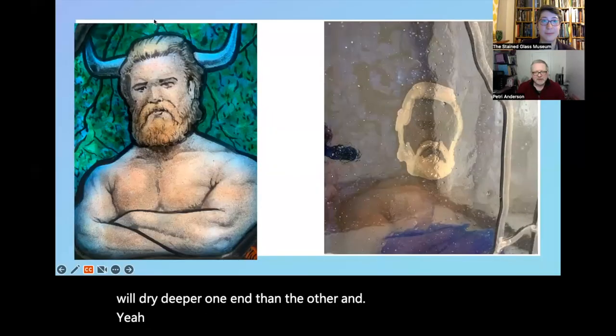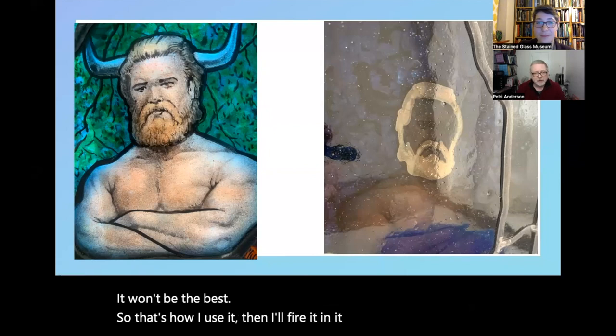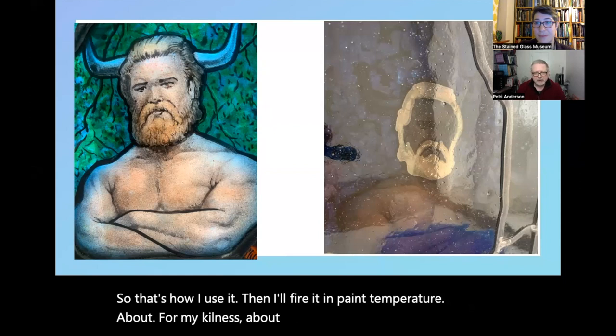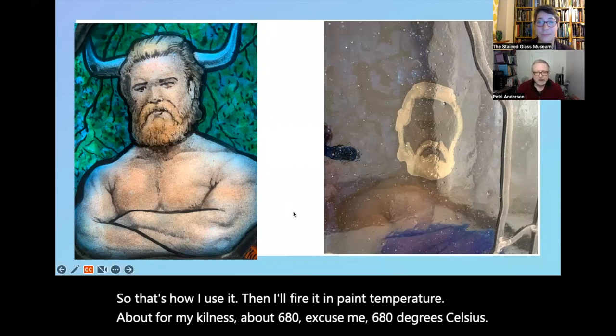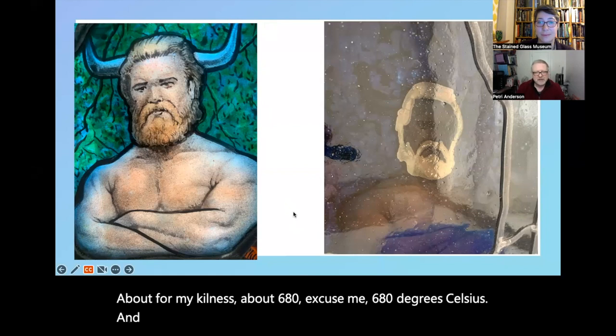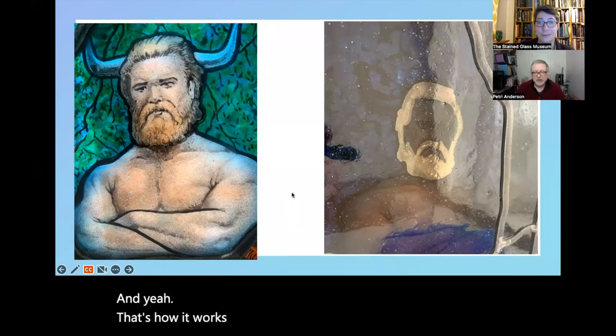And it really works best in small areas. When you try and do a large area with it, then inevitably it will dry deeper one end than the other, and it won't be the best. So that's how I use it. Then I fire it in at paint temperature, in my kiln it's about 680 degrees Celsius, and that's how it works, and it stays as well.